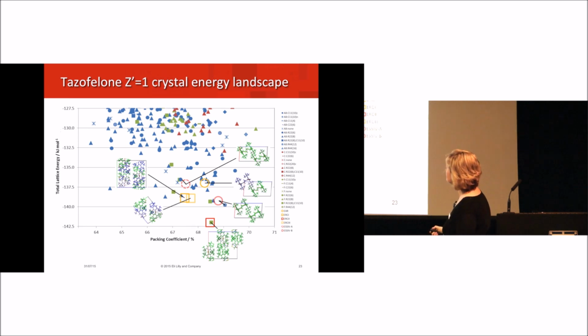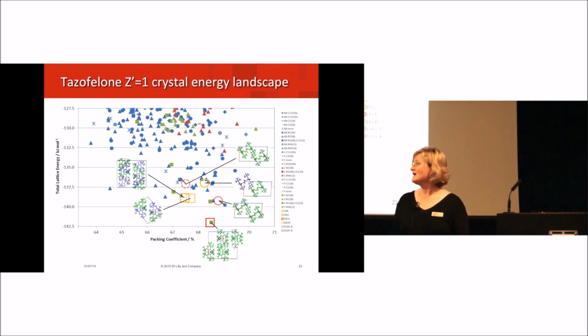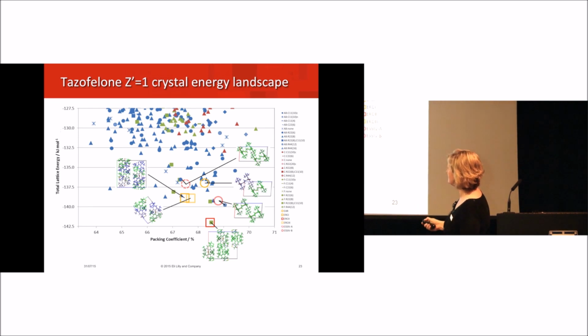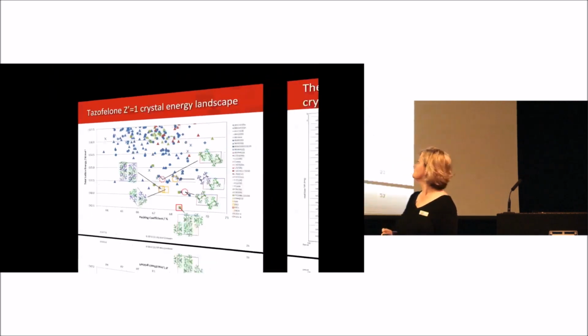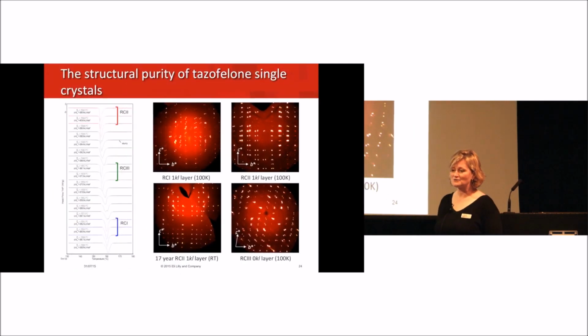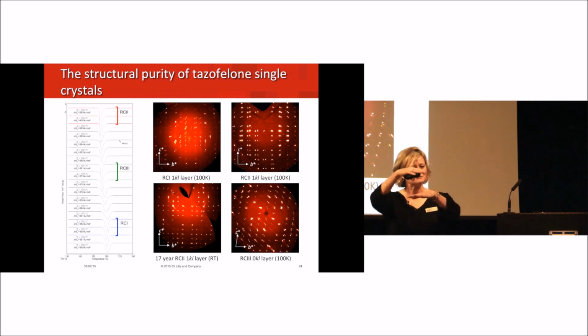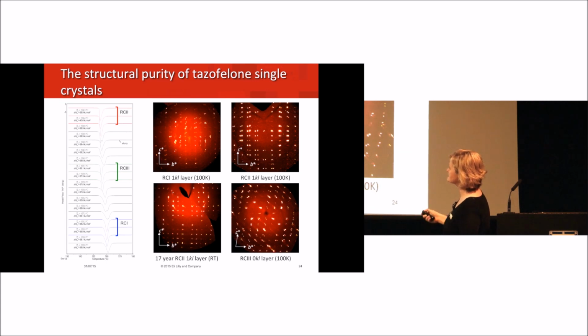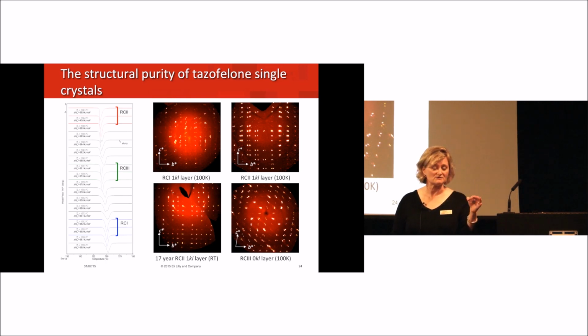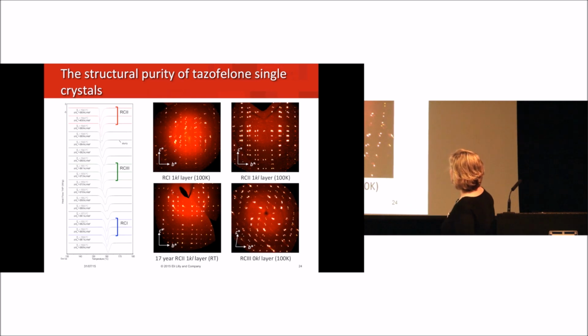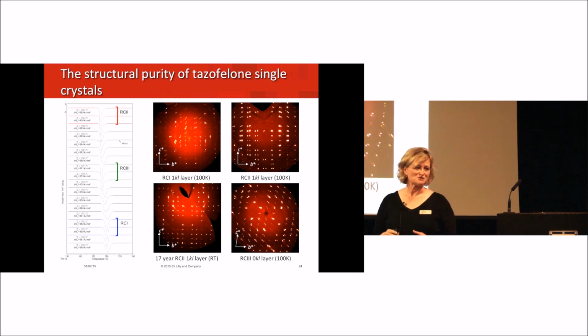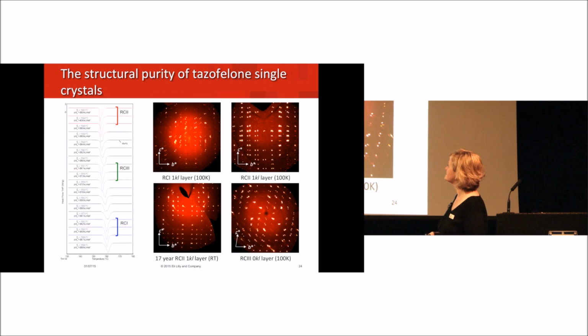But what she has been able to see, in addition to the ones that we have, were different packings that have some strong structural similarities. And that was interesting. You can kind of see it from how I've shown these unit cells. 3 of our racemic polymorphs, in this case, look to have layered structures. It turns out there are other structures that Sally has predicted at low energies that also have these layered structures. And in fact, this underpinned some of the work that we eventually did to show that the crystal forms of tazofelone, in general, the racemic ones, are defective. They all have domains and intergrowths, and in fact, that was borne out initially by our DSC results that we collected on single crystals, where we simply couldn't reproduce our results from single crystal to single crystal. And it later was shown to be the case through analysis of the raw diffraction. So this looks much like aspirin and some of the other notorious examples.